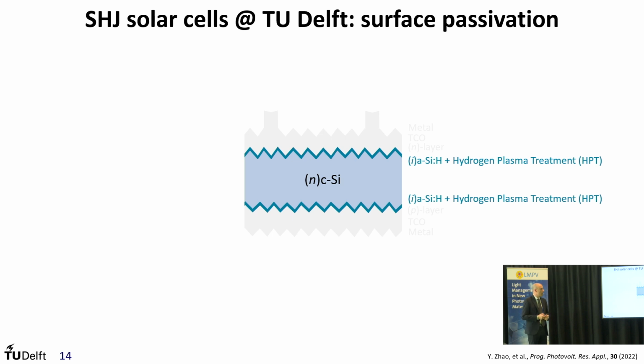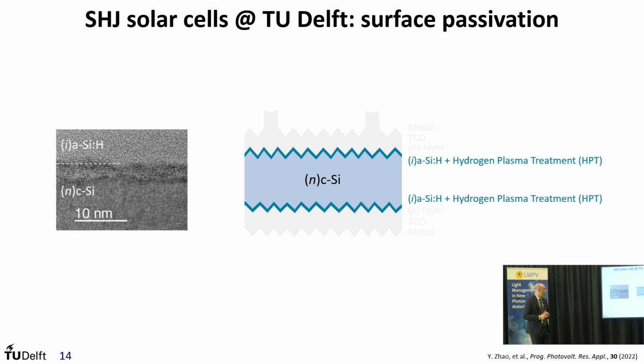And here, next to the intrinsic hydrogenated amorphous silicon, I also mentioned the so-called HPT, hydrogen plasma treatment, that is essentially a way to tune the properties of the amorphous silicon as it grows on top of the 111 crystallographic orientation that comes out of the etching of your 100 oriented crystalline silicon wafer. Essentially, if you don't use this hydrogen plasma treatment, there are high chances that your amorphous silicon will grow epitaxially on your pyramids, giving then a very poor passivation property.